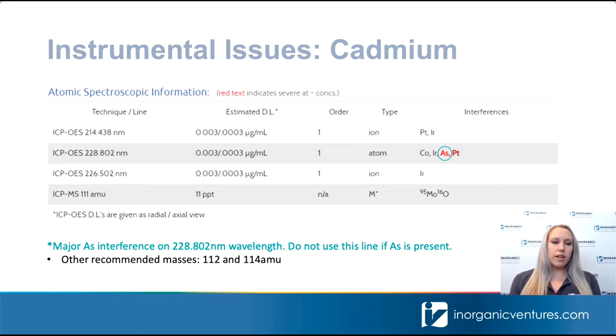And I also wanted to point out again that arsenic is going to interfere on the 228 wavelength for cadmium. So for these types of analyses, you want to make sure to use a different wavelength if you're analyzing on OES. For mass spec, our recommended line is the 111 line, but be aware that molybdenum is going to cause interferences for all of the cadmium lines, actually. But some other recommended masses are the 112 and 114 masses. So you just want to look at all of those and make sure that they are in agreement with each other and you're getting accurate results for cadmium.